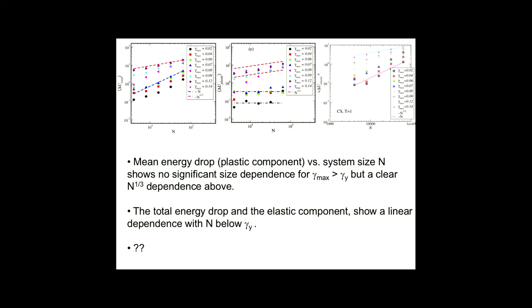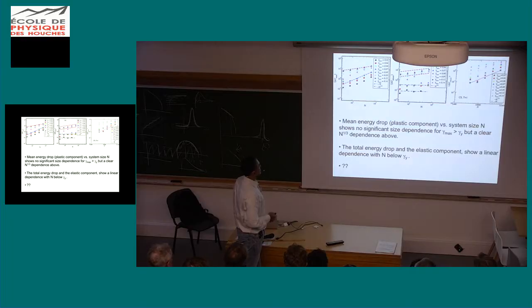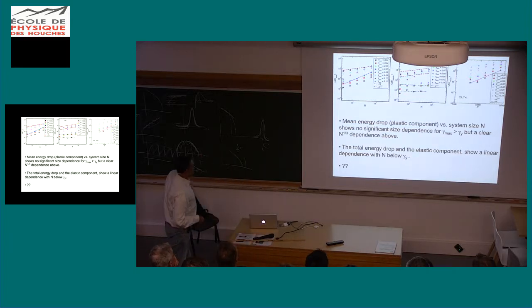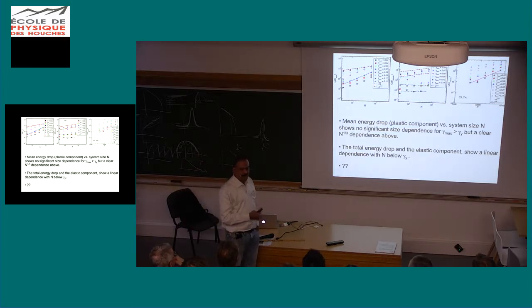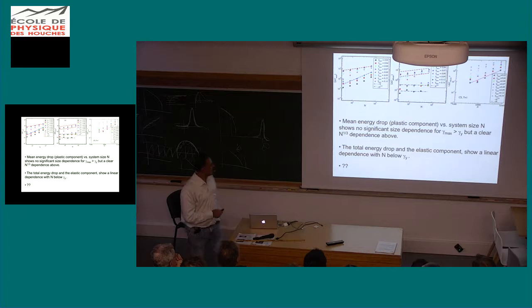And now here's something that I don't understand. If you look at the total energy drop and look at the size dependence, at high amplitudes you have this n to the 1/3 scaling. At smaller amplitudes, a priori it's not very clear what the n dependence should be or whether there should be any at all. But what you see, and this is something that I don't understand, is that the total energy drop below the yielding transition has a linear dependence on the system size.